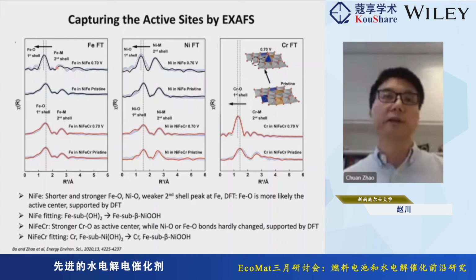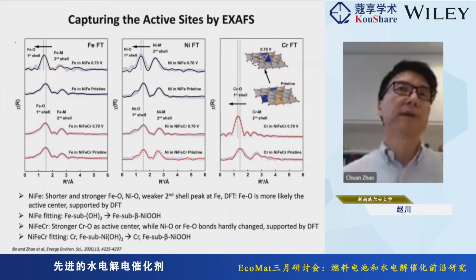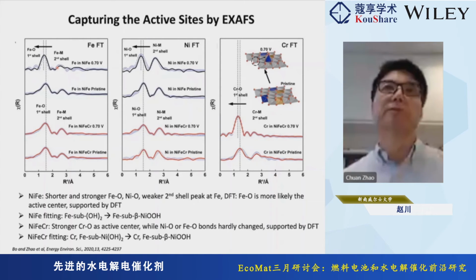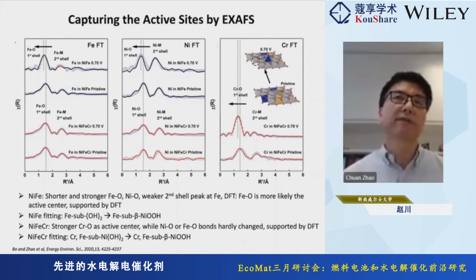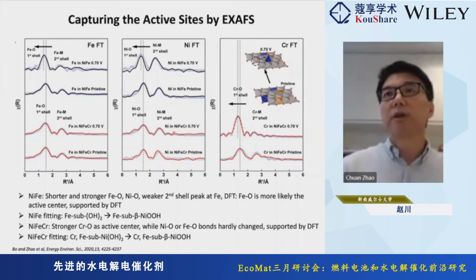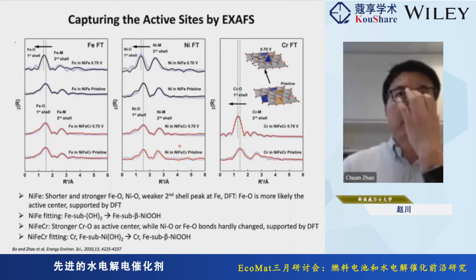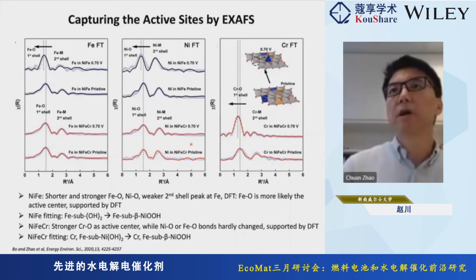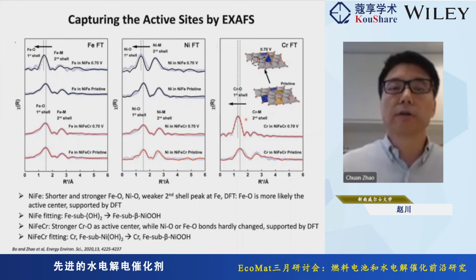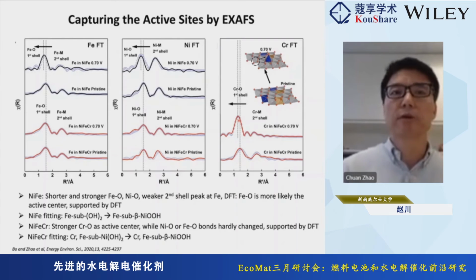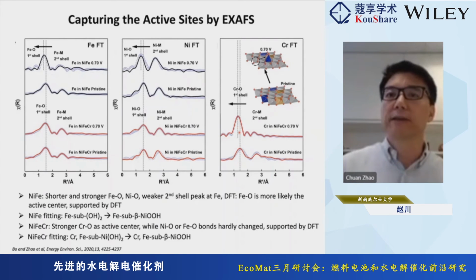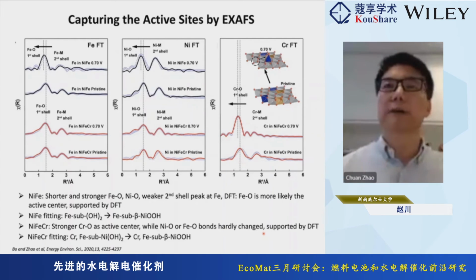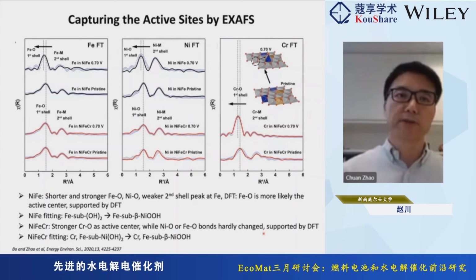So there has been a debate for many years about nickel iron, which is the active site. Some people think it's iron, some people think it's nickel, and our results provide evidence that iron is more likely to be the active site. So in the chromium case, when we introduce the chromium and apply a potential, we don't really see significant change in the nickel and iron, but we saw a significant decrease of the chromium-oxygen bond, suggesting the chromium-oxygen bond is stronger and is the active site. And we also did some DFT calculations which support that chromium can be the more active site for OER in the nickel iron chromium system.